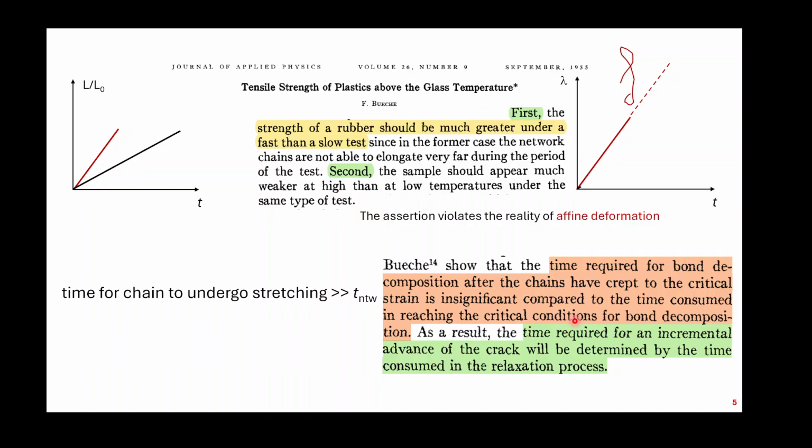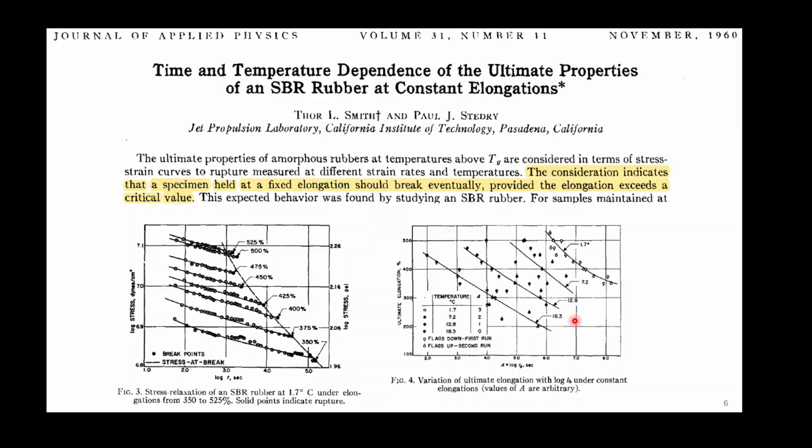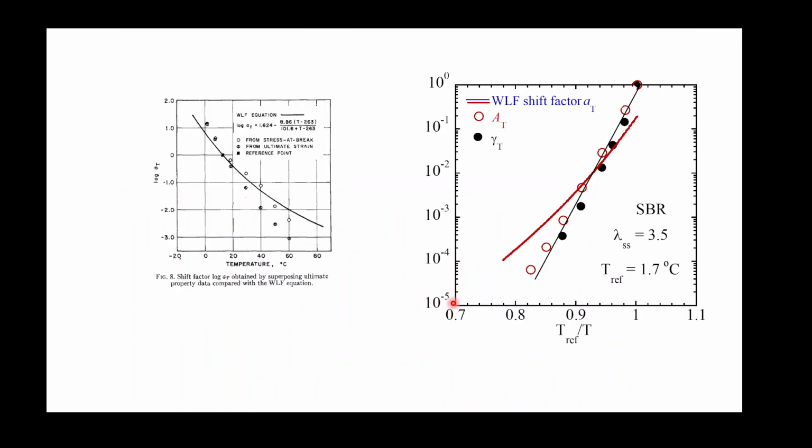I want to show that exactly the opposite is true, based on experiment. Moreover, there's this more magic experiment. You do a step stretching. You find that if you stretch to this level at lower temperature, it will, this is called delayed rupture. You hold it over time, and it will rupture. The more you stretch, the less time you wait for rupture to occur. At lower temperature, it takes longer time. Notice that parallel curve. You can do a WLF shift again, and in fact, he did, and he compared with WLF.